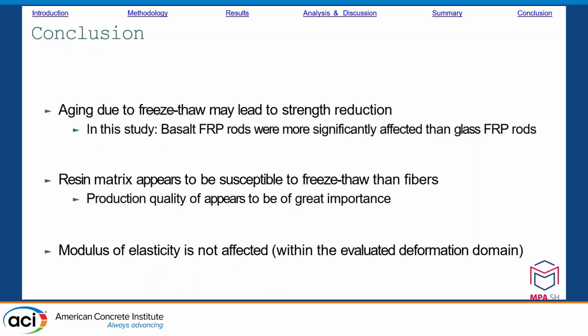In summary, it can be said that the freeze-thaw load leads to a reduction in the strength properties of the FRP bars. This is greater for the basalt rods than for the glass fiber rods. The resin matrix is more susceptible to frost than the fibers. The production quality of the reinforcing bars also plays a decisive role when it comes to frost resistance. The better the production quality, the better the tensile and shear strength properties. The frost load had no influence on the modulus of elasticity when these tests were carried out.